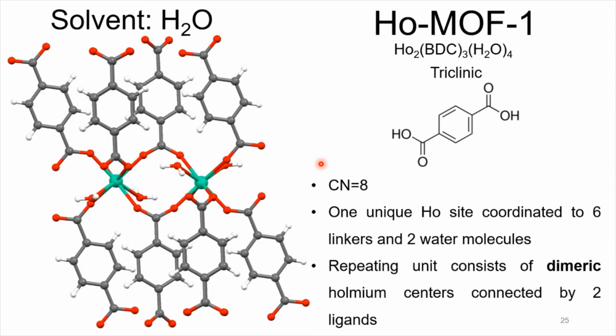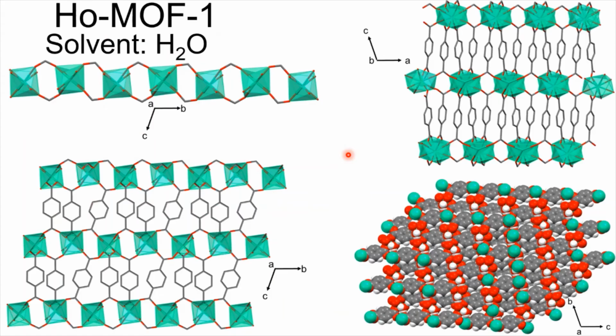structure. But it's made of dimers. So there's 2 Holmiums that are the core of this repeating unit. And as you can see here, these dimers repeat over and over to make a chain. And then these chains are linked by the ligand, terephthalic acid, in both this direction and this direction. So you end up with a 3D framework. Now, in this case, this is not a very porous framework, but it is still a MOF.